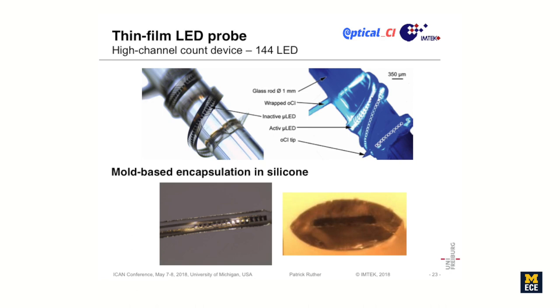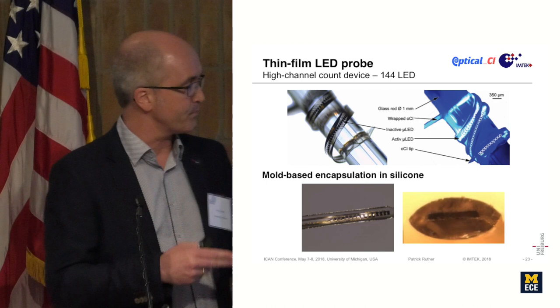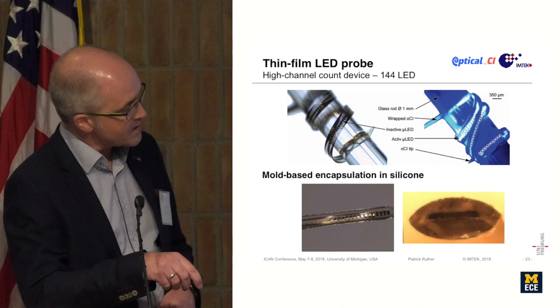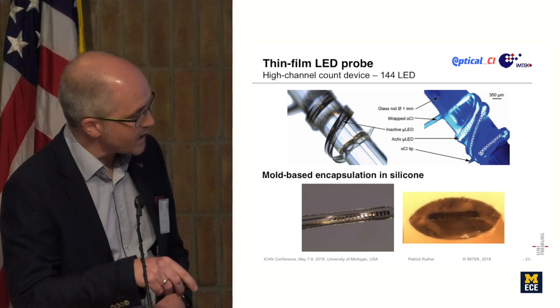So what you see here in dark is the substrate, either polyimide and epoxy or purely epoxy. And Eric developed a mold-based process that allows us not only to coat the back and front side of the probe, but also the sides here, which is most critical in view of application.